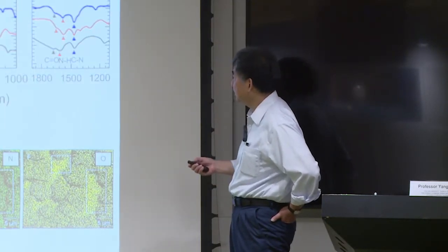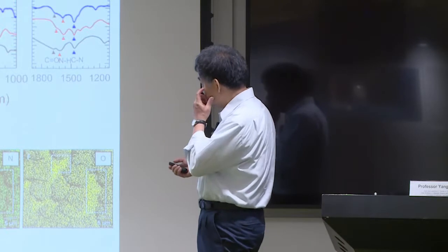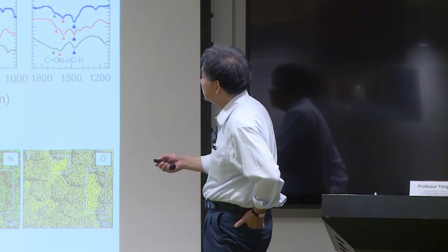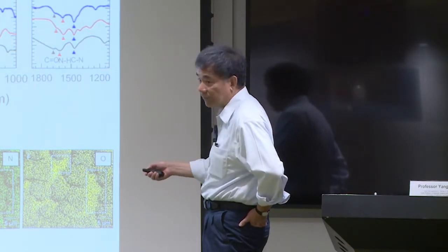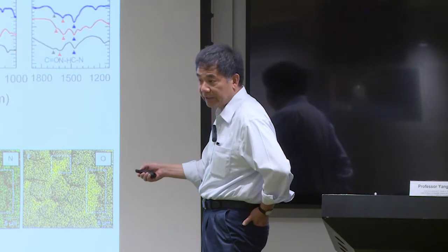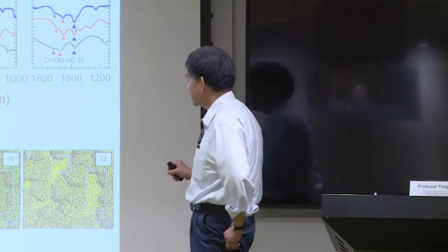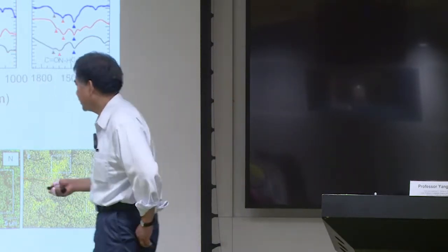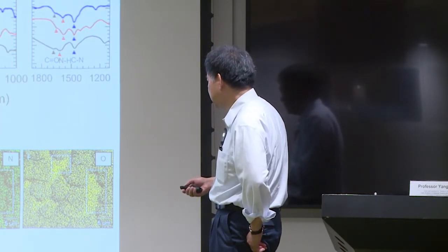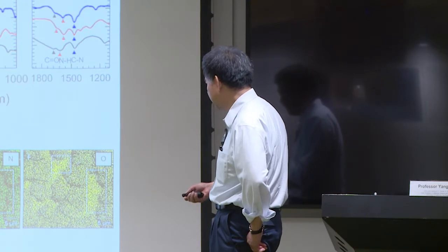So that's the urea, and you can see from the TG data that DMSO and urea decay at a much higher temperature. We are baking the film at 150 degrees C. This indicates that the urea still stays in the film. And where does it go? We have done this EDX, the element analysis, with SEM. One can see the urea actually goes into the grain boundary.